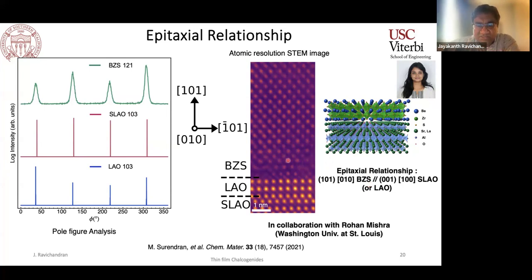We also noticed that there's significant interfacial damage in these cases, presumably because of argon or even the hydrogen sulfide reacting very aggressively with the oxide substrate underneath. So while we could get a reasonable idea of what the lattice matching and the epitaxial relationships are, the interfacial quality was not as impressive as we would like it to be.